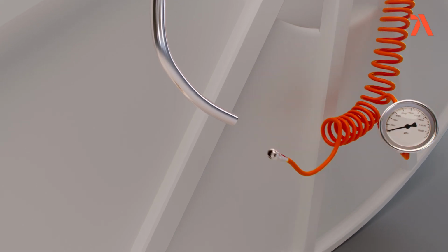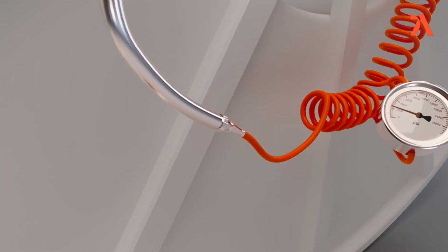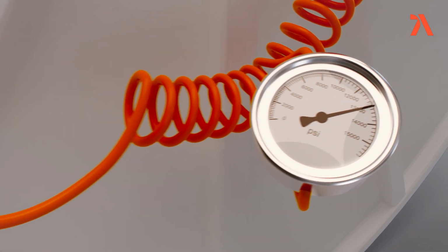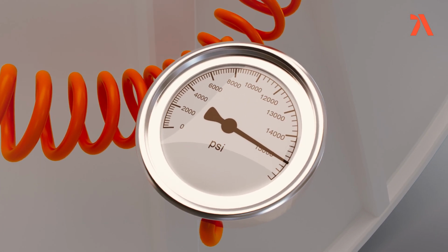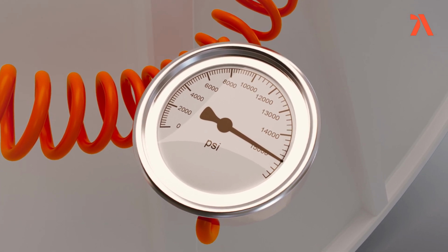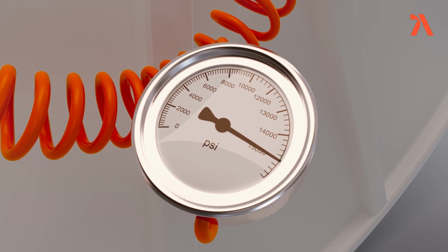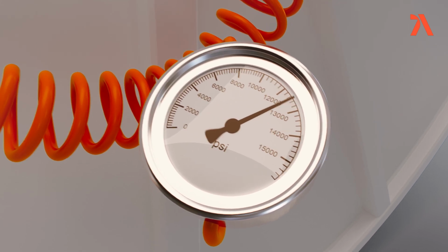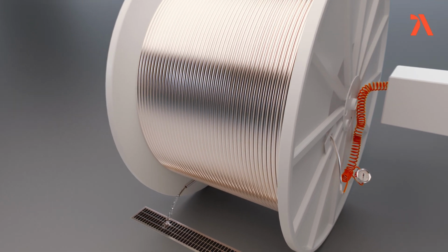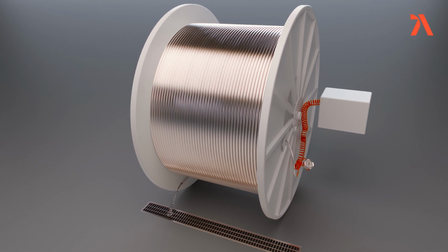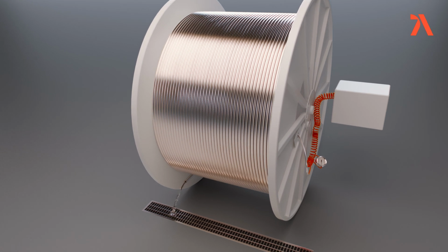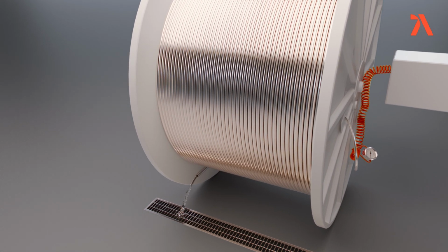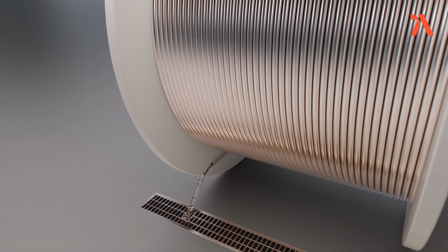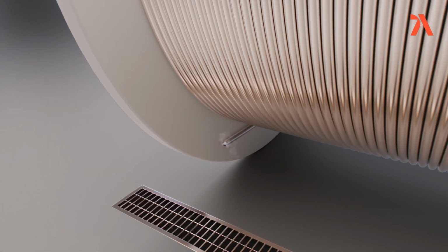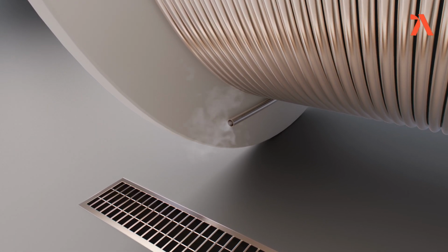After coiling, the umbilical tube is subjected to hydrostatic testing, where it's pressurized to 1.5 times the desired pressure, maintained for a minimum of 4 hours. The tube is then flushed with water and its internal cleanliness verified to ensure SAE AS 4059 Class 6 compliance or better. It's then emptied of water, blown dry with nitrogen gas to meet the required dew point, and its ends are plugged.